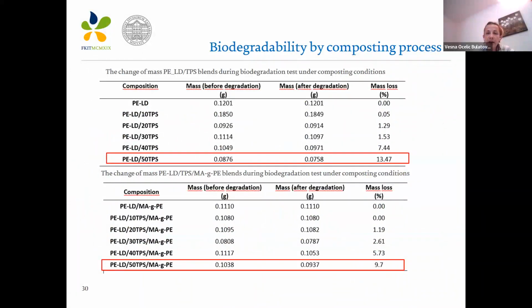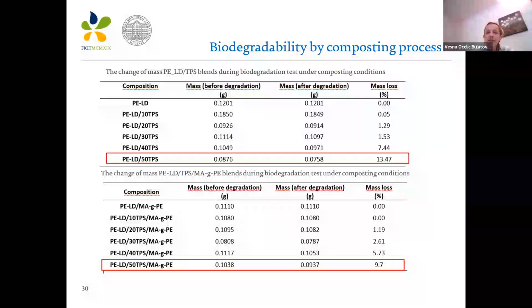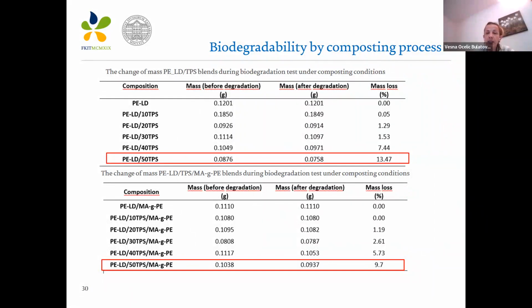On this slide is the table relating to the results of change of mass for the blends during the biodegradation test under composting conditions. Pure polyethylene shows no mass loss during the 16 days period of the composting process. TPS was completely degraded during this process because it is very hydrophilic and serves as food for the microorganisms. In the compost, the microorganisms recognize the carbon bonds of thermoplastic starch as a good source of nutrients.